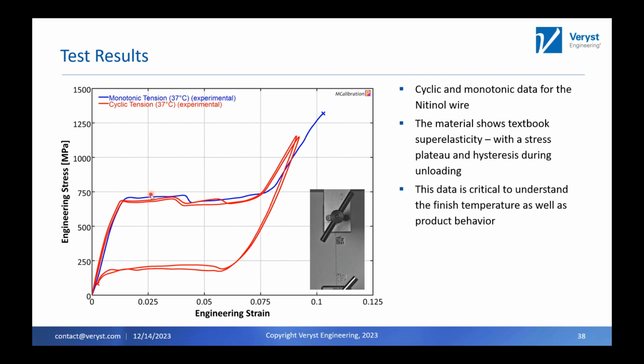And I always get this backwards, so I apologize. Going from the martensite to the austenite phase transformation. And then at this point, all the material has transformed. It stiffens up. And then as you unload, you actually follow a slightly different path. And then as you're going along here, you get the phase transformation back the other way. And then you can reload again. And then this blue one was tested to failure.